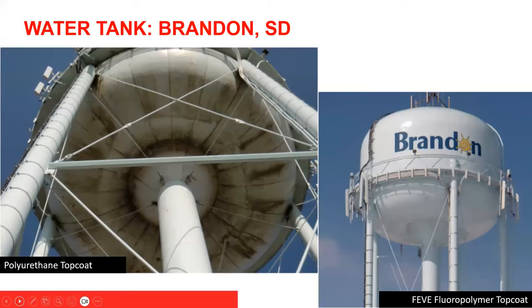Here's another case of a water tank. Water tanks are very tricky because they tend to have a lot of condensation on them that encourage organic growth. Polyurethane on the left, the belly of that tank where a lot of that condensation forms, had a big mold and mildew issue. And the fluoropolymer on the right, after it was coated, looks much better and is maintaining that appearance over time.